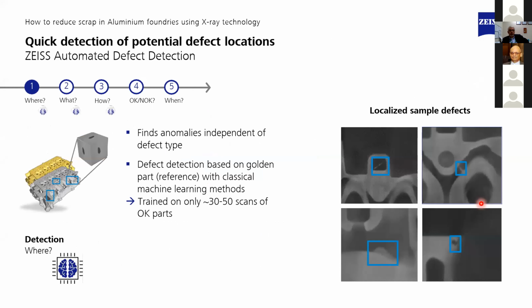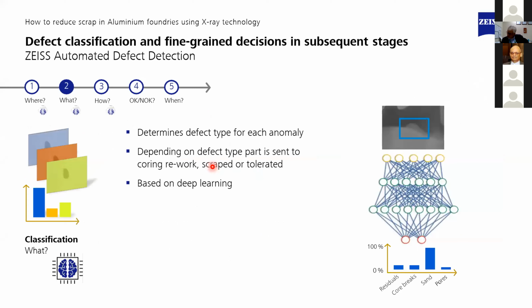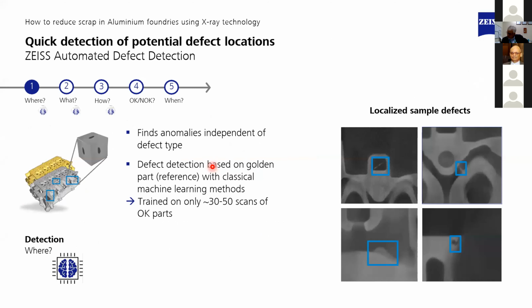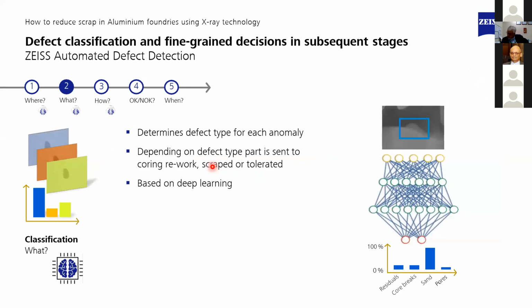So in the first step, we are trying to find out what kind of defect it is, whether it is an internal defect or external defect, like sand core or chips, which is entrapped inside the casting. And then we identify what type of defect. Is it a residual or core breaks or sand or pores? So all this analysis is going on in the back end. When the scanning is done, this whole thing happens in about a minute.